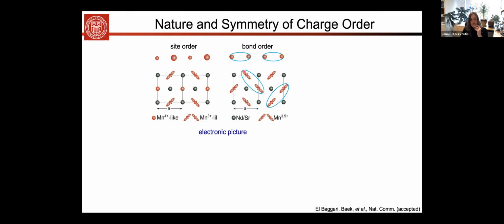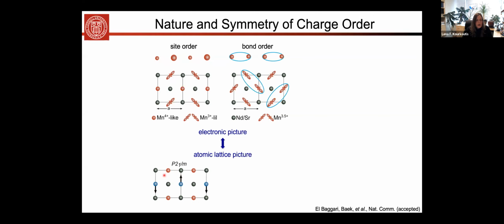Now, this is the typical electronic picture that you see in the literature, these orbital-ordered structures. But what you should not forget is that there's an atomic lattice picture. That means the atomic lattice can respond and can distort. And so here, what I've now done is color code the individual manganese sites. And you see that in this particular site-centered phase, the first manganese atom will displace downwards, the second will be stationary, the next one will go up, 0, down. So we have a down, 0, up, 0, down movement. Okay, this is the site-centered symmetry.